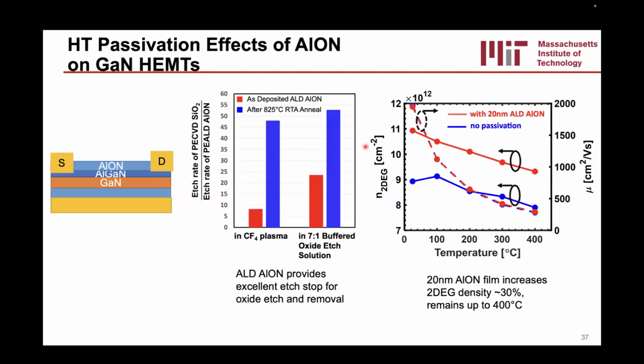And additionally, the nice thing about this film is it also acts as a passivation layer. If you look at samples that have no passivation and devices that have passivation, you can see that the 2DEG density increases about 30%, and that increase is sustained up to high temperatures, 400 Celsius. While the mobility, which is in this dash right here, it's a little hard to see, but they're right on top of each other, so the mobility doesn't really increase at all.